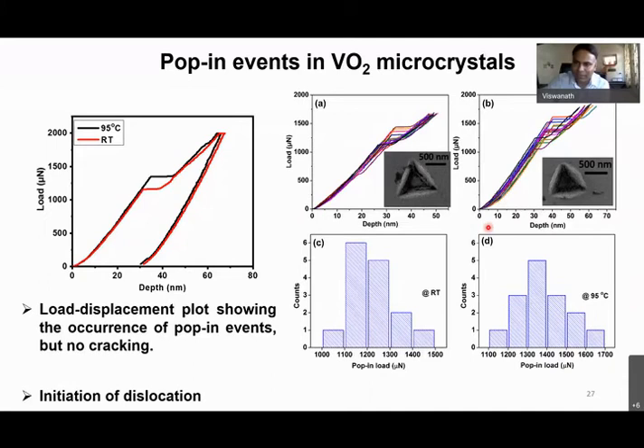And the difference between these two is probably very difficult to pinpoint. The scatter, we are able to see around 1500 micronewton of the difference. So pinpointing will be a little more difficult, but there is a difference in their actual threshold load required for initiation of dislocation. I think I don't have the values. In fact, we have seen the elastic modulus and hardness below the popping and above the popping event. And we also tried to calculate the shear stress. Probably I have removed the table.